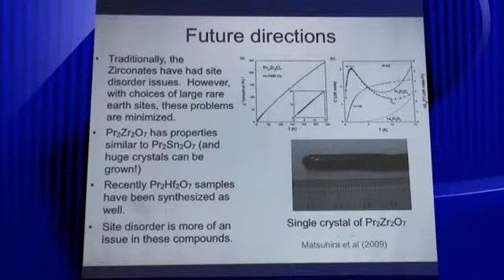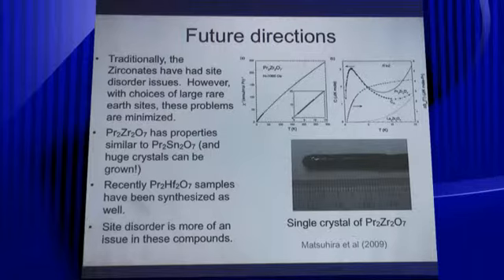But there are some Japanese groups, around Matsuhira et al., for example, that have shown you can grow very large single crystals of these compounds. From a chemistry perspective, the crystal growth is challenging because zirconium oxide doesn't melt till extremely high temperatures. So you have to get in the order of 2500 C and higher. And at those temperatures, you're losing your rare earth oxide as well. So you have to add extra praseodymium oxide in this case in order to get the right stoichiometry to counterbalance what you're losing, right? But there's some preliminary evidence that suggests there could be interesting spin ice-like states in these compounds. But again, this is in the very early days.